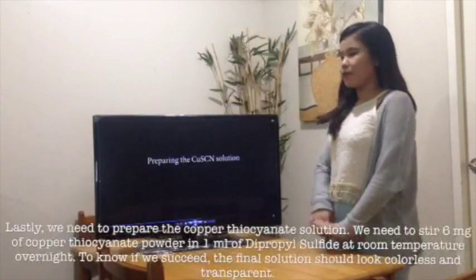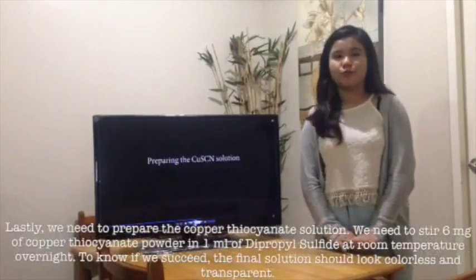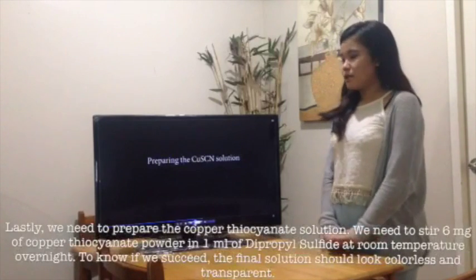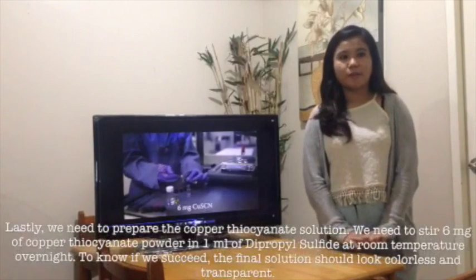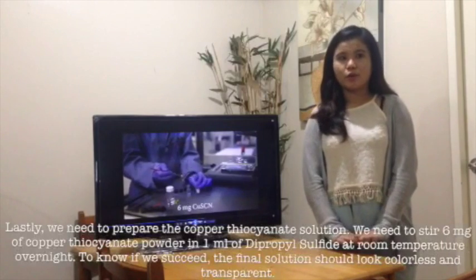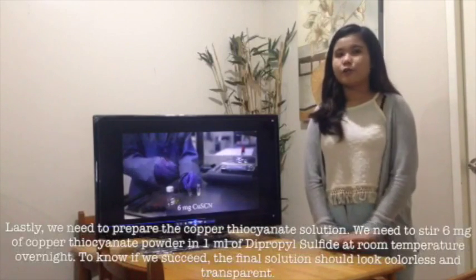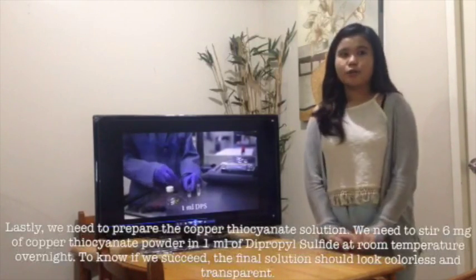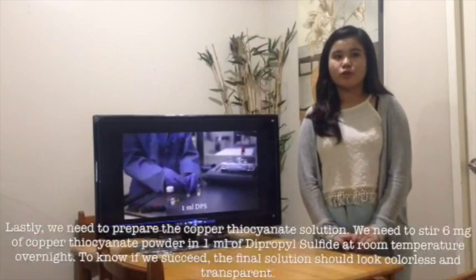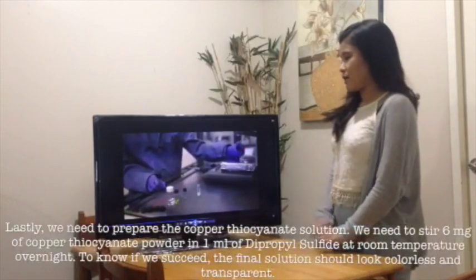Lastly, we need to prepare the copper thiocyanate solution. We need to stir 6 mg of copper thiocyanate powder in 1 ml of DPS or dipropyl sulfide at room temperature overnight. To know if we succeed, the final solution should look colorless and transparent.